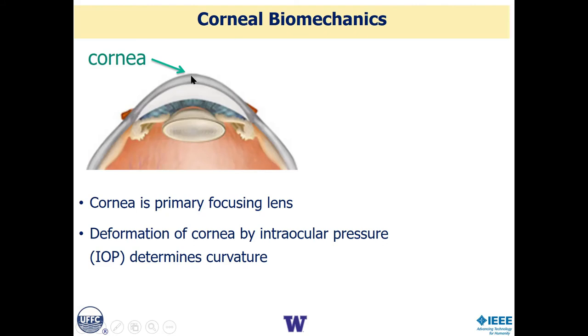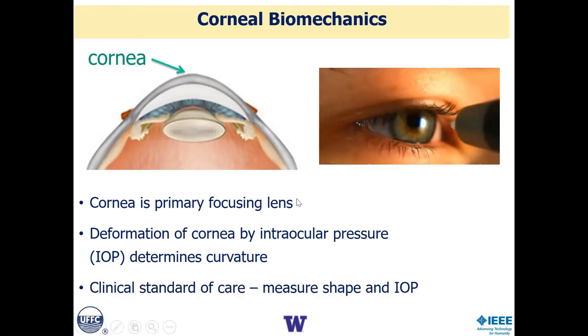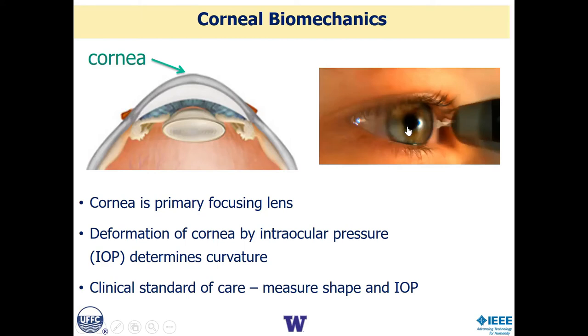So elastic properties are directly linked to shape, which is directly linked to the optical performance of that lens. The clinical standard of care is to measure the shape optically and to try to estimate the IOP using a force deformation measurement, which assumes characteristics about the elastic moduli of the cornea. The elastic moduli are not measured, and therefore that can both confound IOP measurements and also not allow you to predict shape changes as a result of therapeutic interventions.